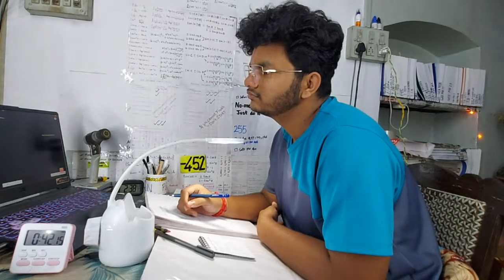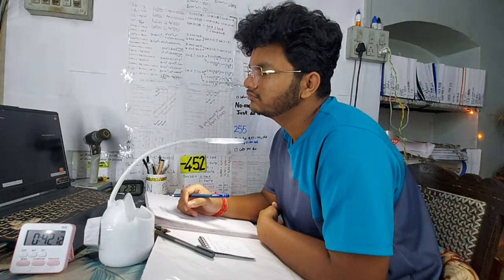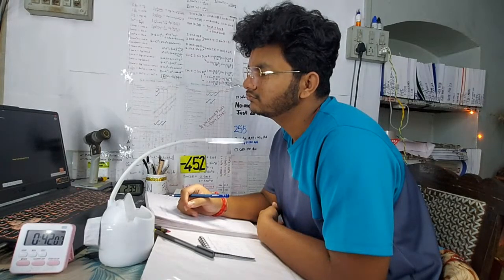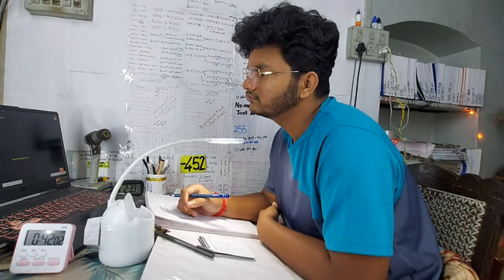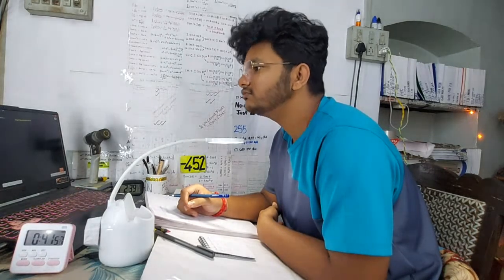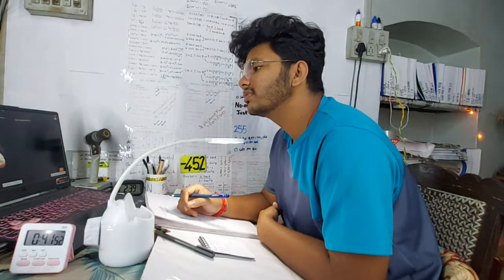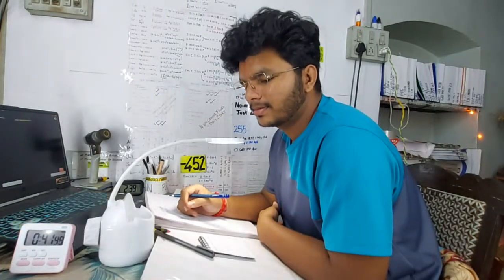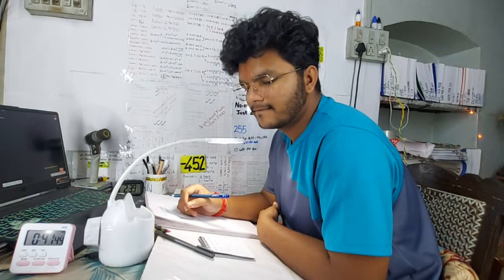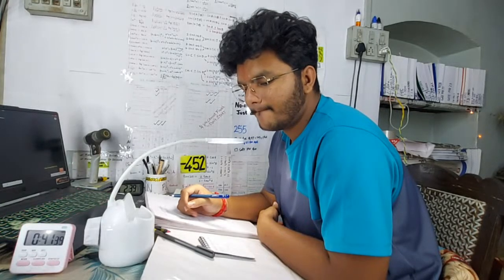Second sample: take austenitized eutectoid steel, rapidly cooled to a temperature like 600 degrees centigrade. At time t equal to 0 seconds, we started holding it at a constant temperature. Then, at that constant temperature, hold the specimen under the microscope and find out at what time the austenite to pearlite transformation begins. Let us call that B2. Similarly, keep watching in the microscope and find out the time at which the transformation is complete, called E2. E2 is the ending time of austenite to pearlite transformation at 600 degrees centigrade. B2 is the beginning time of austenite transformation into pearlite at 600 degrees centigrade. 0 seconds to B2 seconds is called the incubation time at 600 degrees centigrade.